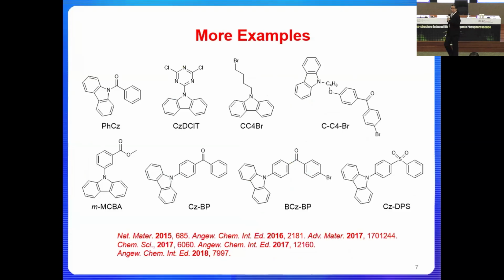We were surprised, but it's very difficult for us to convince the community that there are mistakes in the literature, particularly for the record-holding molecules for room temperature phosphorescence. So we spent a lot of time looking into other molecules of great promise that have been reported in the literature. As you can see from here, these are all great papers in top journals. And each paper is reporting one of these molecules or a combination of them. It's very interesting that all these molecules, if you resynthesize them from pure laboratory molecules, you will not be able to reproduce the phenomenon reported in the literature.